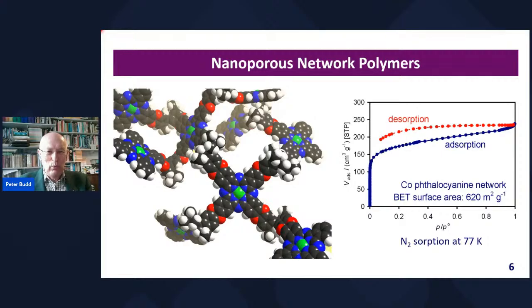So even relatively weak interactions with the surrounding polymer are magnified just because of multi-wall interactions. And that's why a particular feature of these materials, called microporous materials in this context, is to get very strong adsorption at very low relative pressure. And so typical examples are things like zeolites and activated carbons,